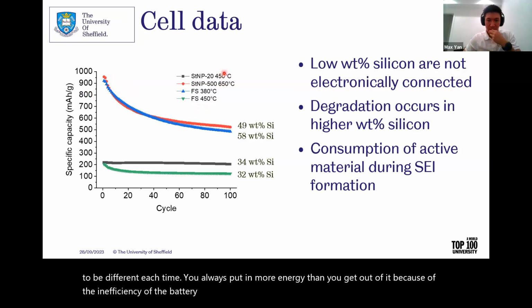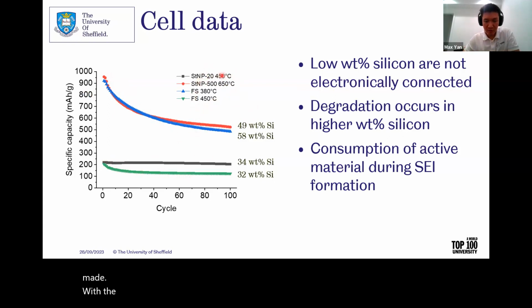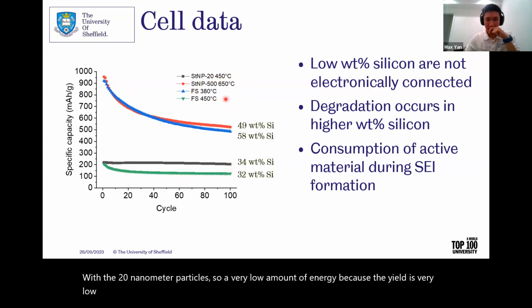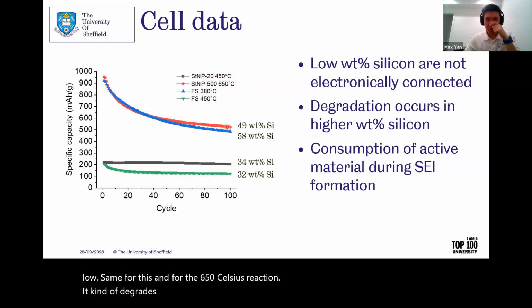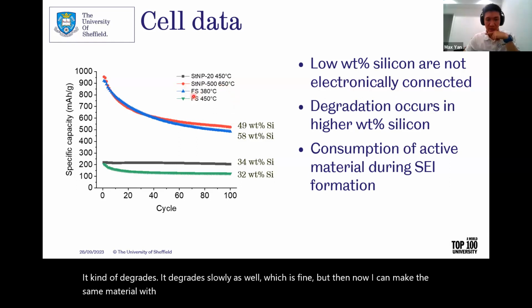And so you can see with different silicon that I've made, with the 20 nanometer particles, I store a very low amount of energy because the yield is very low. Same for this, and for the 650 Celsius reaction, it degrades slowly as well, which is fine. But now I can make the same material with fume silica, 7 nanometers at 380.